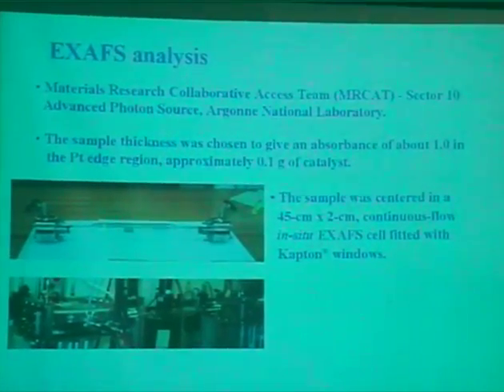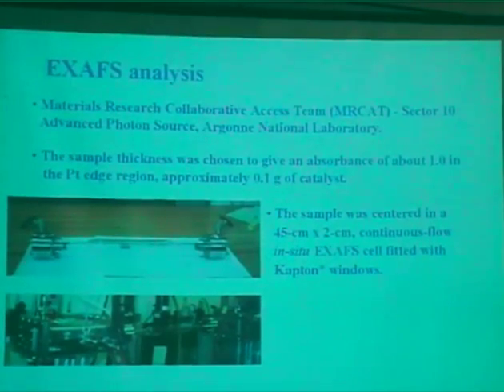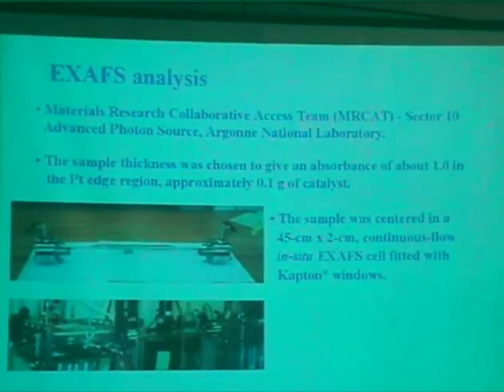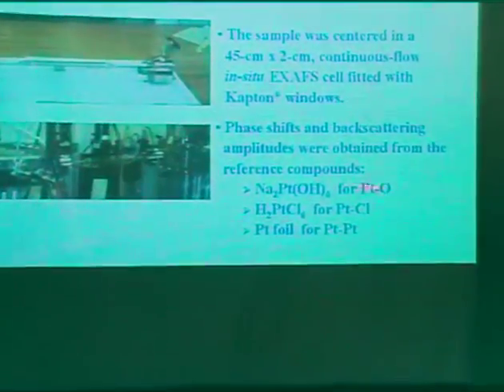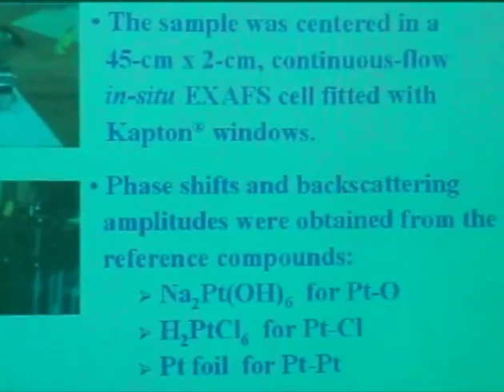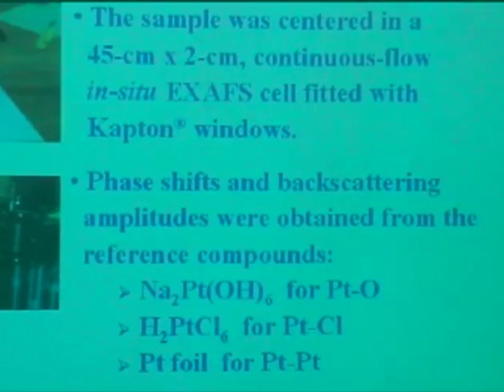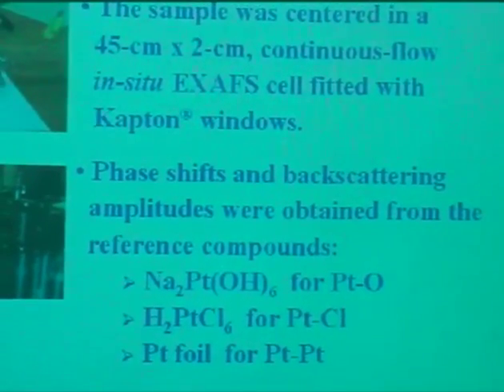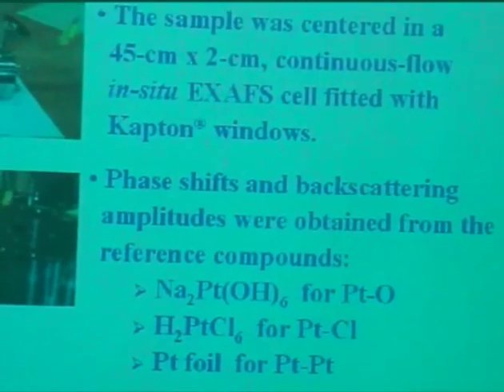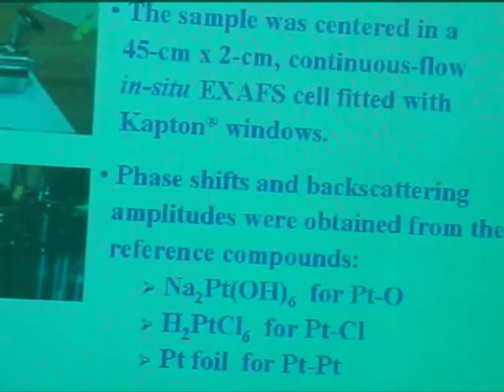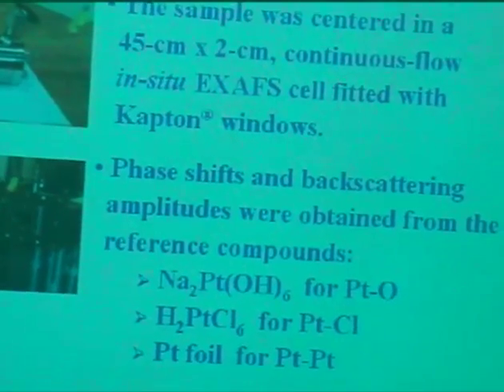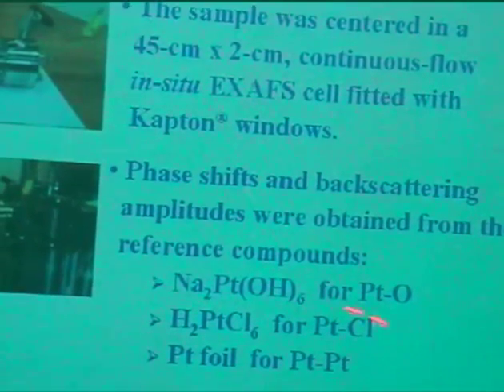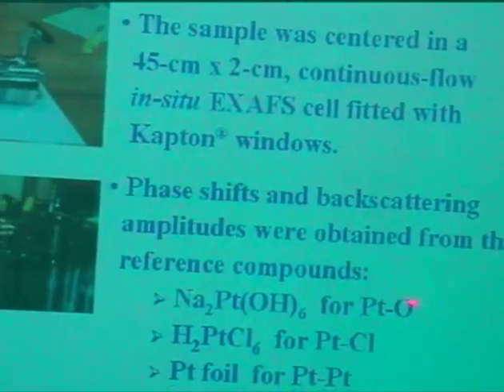We do all this at the Argonne National Lab, and we put it in the beam. These are the two detectors. And we do this in a continuous flow. This is where the furnace is. And we obtain the data at conditions after pre-treating under various conditions. And the key about XAFS is that you have to have very good standards. Otherwise, you can do a lot with your fits, because there are lots of parameters there. And I don't know much about it, but Jeff is very much an expert, and he's done a lot of samples. These are the standards that he uses for assigning all these distances and coordination numbers.